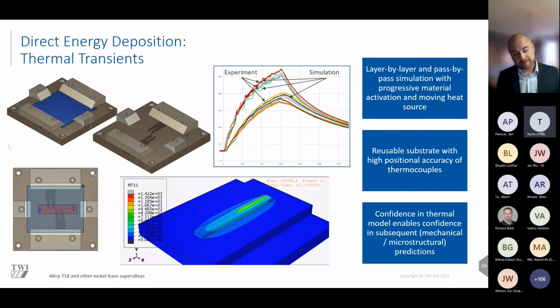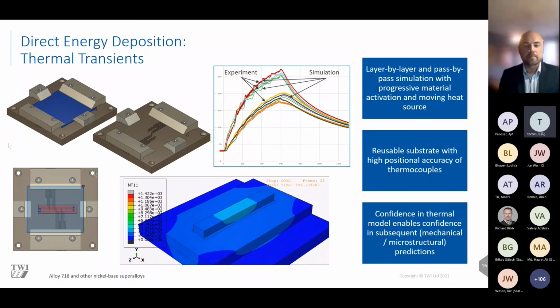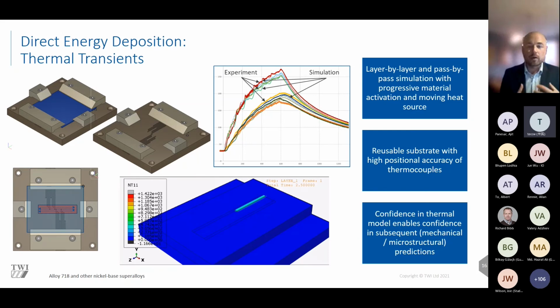And again, we like validation. So as opposed to sticking a thermocouple substrate, here we have a reusable, recyclable thermocouple substrate where we can place contact thermocouples underneath a part or underneath the build plate, build directly on top of that. And this is so important for that confidence in your thermal model before you start running ahead to distortion and residual stress and microstructure. And the nice thing is you can just unclamp it, put something else back on it, and deposit in different styles and replicate that in your model.